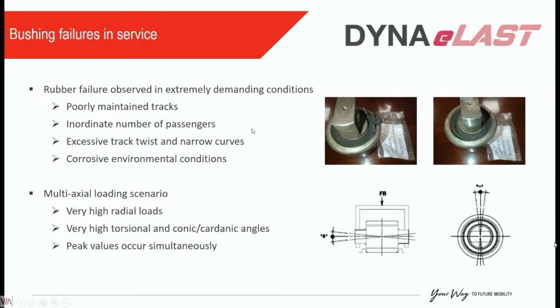Like I said, originally we didn't really pay much attention to these elements. They are not safety critical. But as we started having problems and customers complaining, we needed to pay more attention to them. So we tried to understand the problem. It is a multi-axial loading scenario where we have very high radial loads, very high angles, both in torsion and in conic or cardanic axis. And what we saw is that the peak values of all three of them occur at the same position.